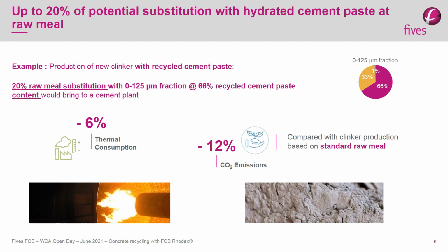One of the routes to valorize the fines is to put them in a raw meal mix at the cement kiln inlet. Without compromising the chemistry, up to 20% of raw meal can be replaced by the hydrated cement paste. The substitution could lead to a potential reduction of 6% of thermal consumption and 12% of CO2 emissions. So, this route is an important means for cement producers to reduce their CO2 footprint.